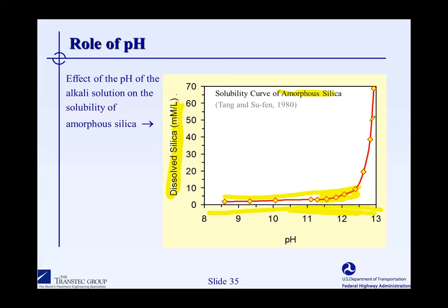Another thing that affects the solubility of silica that's not shown in these slides is temperature. As the temperature increases, the solubility of silica will increase too. And even some relatively insoluble forms of silica, like well-crystalline quartz, will start to dissolve and therefore become reactive if you go to very high temperatures. Quartz itself becomes soluble and reacts at temperatures in excess of 120 or so degrees Celsius, something like 240 or higher degrees Fahrenheit. That doesn't normally affect us in concrete, of course, but it can affect us if we're looking at accelerated test methods where we use very, very high temperatures to try to accelerate the reaction of aggregates.